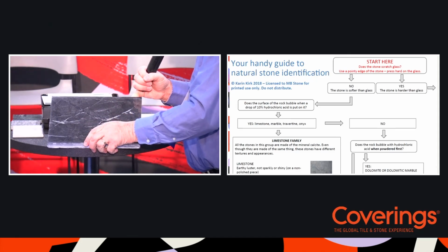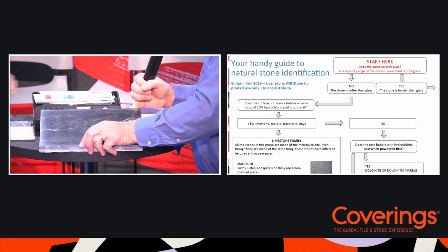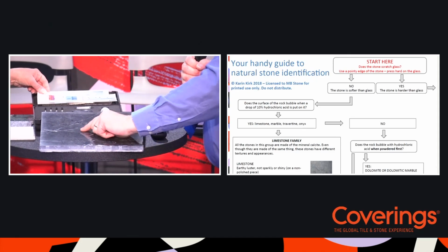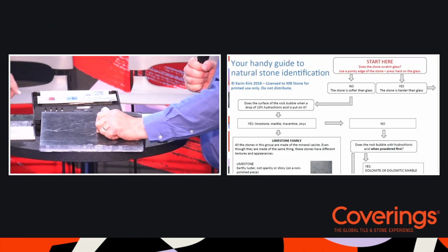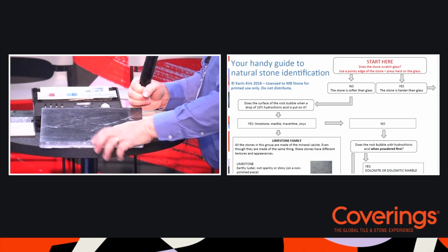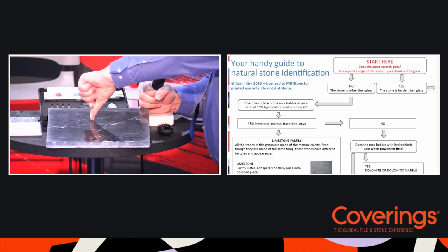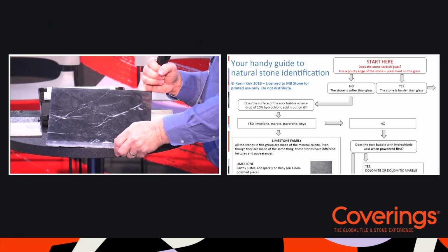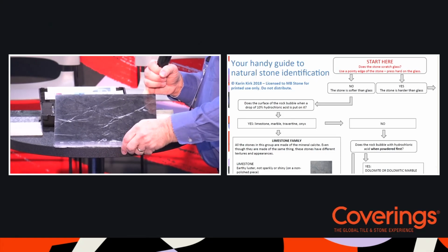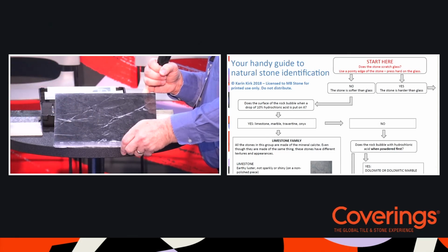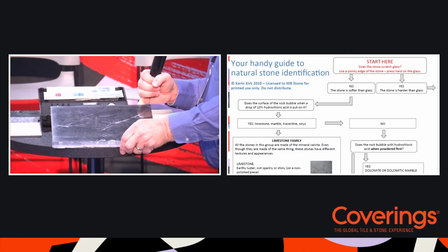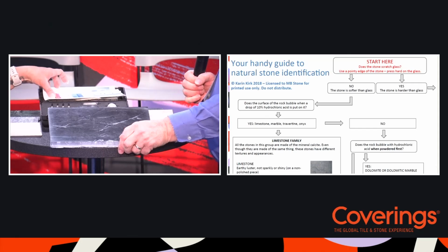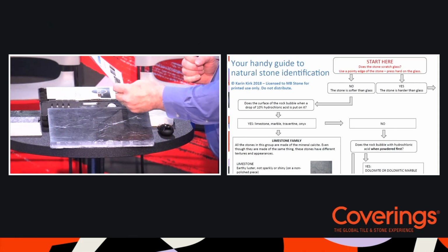So that's a 5 on our scale then. The 4 left marks, but I think that's just surface metal. Yeah. So the 5, you can feel it catch. You can feel the difference when you run these picks over it. If it just slides across it, that's not it. It's the one that grabs. Those faint marks on the sides are just residual metal from the pick, whereas the one I can feel makes a scratch. That's a 5. And I can't see that.